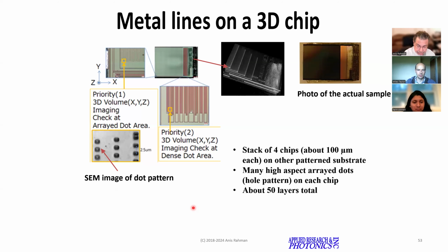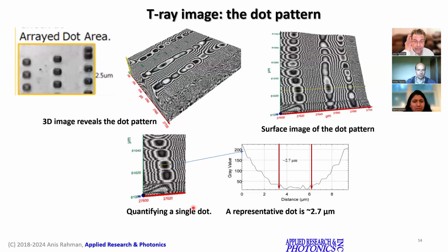But this is an example to show that, on the left is an SEM picture. So we have measured the dots, their size and their separation. The SEM image shows 2.7 or 2.5 or so micrometer separation of these dots. We come close to 2.7 micron. So this is within the experimental error limit. But you can see clearly where the dots are. Not all dots are equally separated.